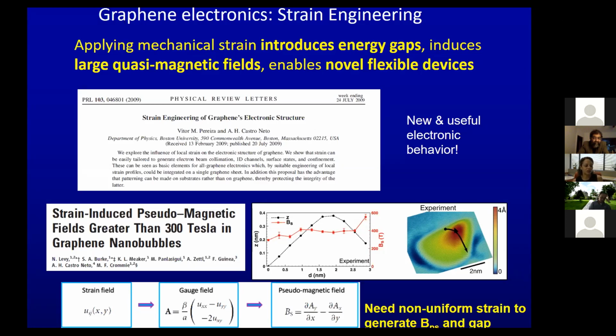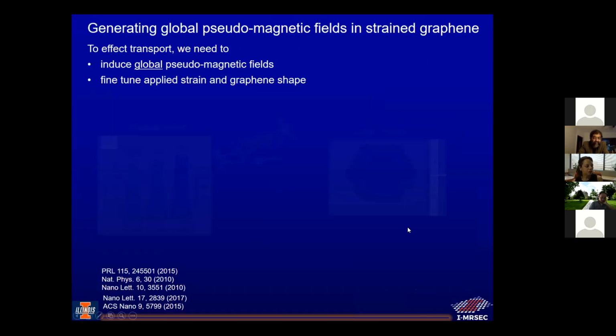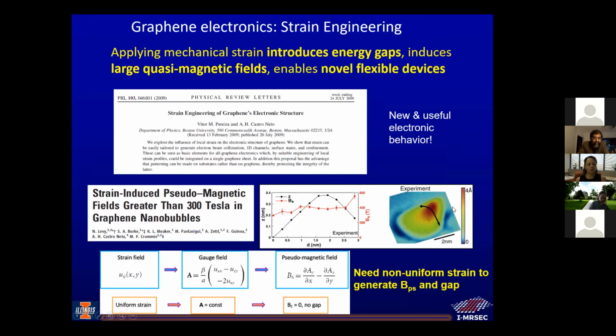And this is what I keep pointing to. If you look here again, we've been talking about how you model it and what it looks like. This is a topography image. This is not a strain image, even though it looks like a strain image. This is topography, right? But it does show you the sort of feature that they have and the length scale. It's not a perfect pyramid, and the graphene does seem to conform to it pretty well at that point. Although at the bottom you can see graphene, and I'm assuming that graphene releases strain at the bottom, and then it sticks to the substrate in between. Right, but from this particular experiment, they could directly measure these Landau levels comparable